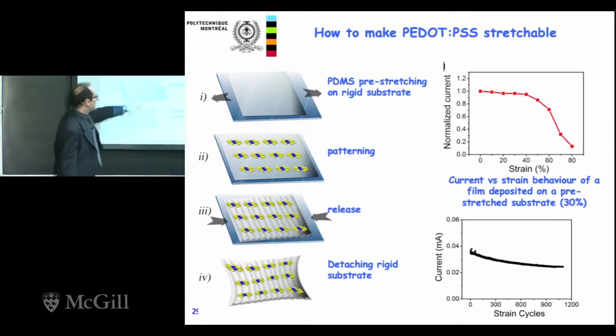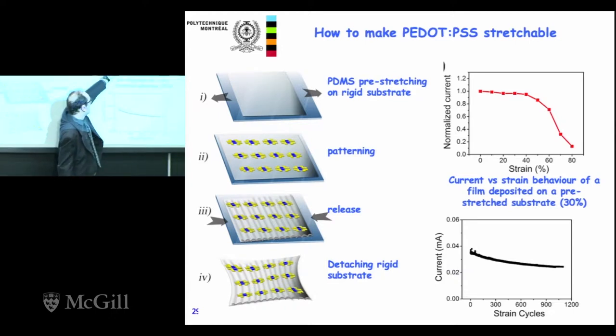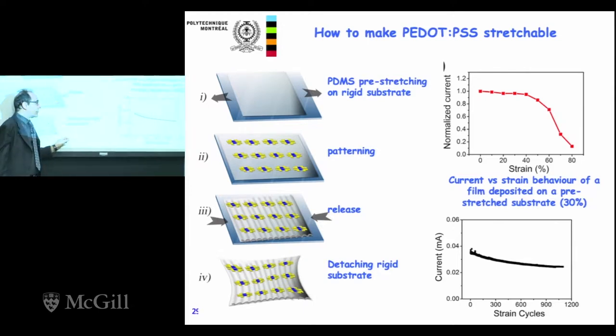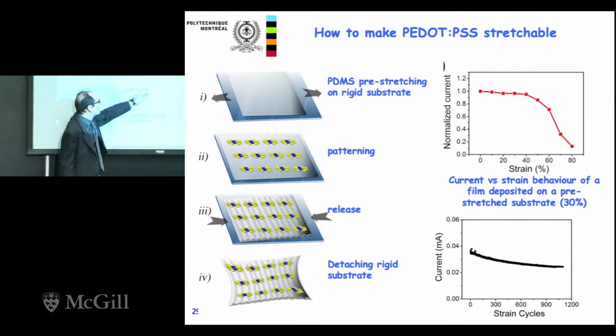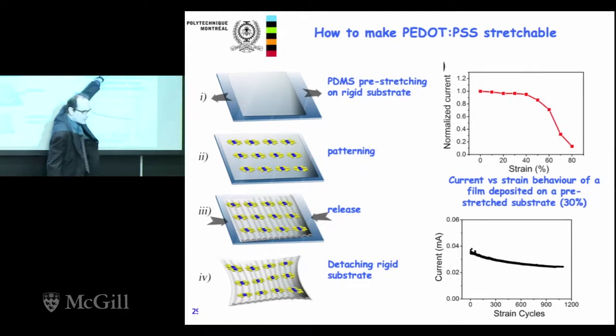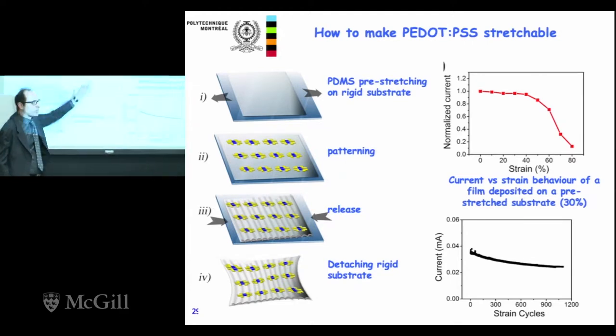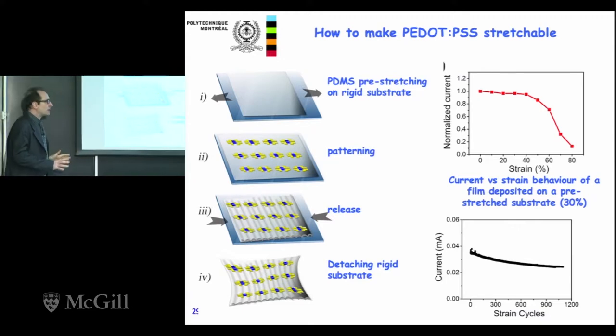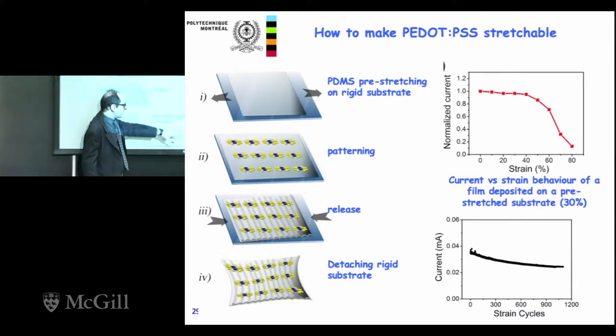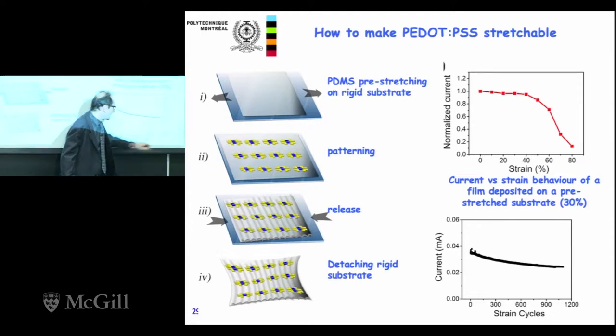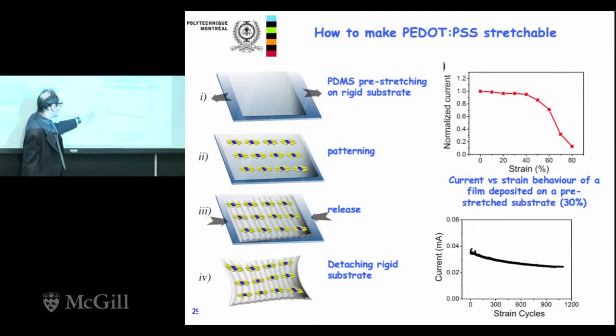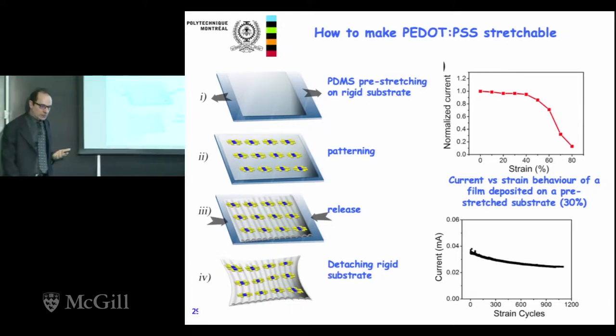What is very nice here, you can see here, this is the current of the device versus strain. You can see that by using the buckling method, you have a stable current up to 40% strain. It starts to decrease after 50%, but up to 40%, you have quite unchanged current characteristics. And if you look at the cyclability, of course, these are more than 1,000 strain cycles between 0 and 40%. And you see that the current decreases a little bit, but you still have something which is conductive after thousands of cycles, which is quite remarkable.